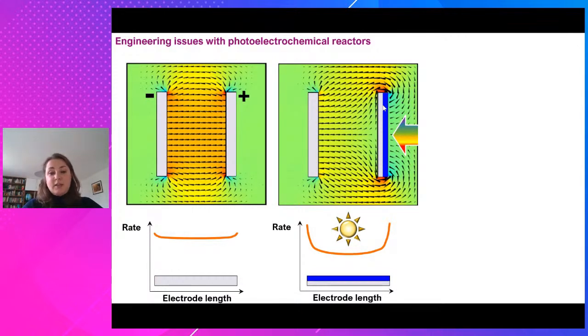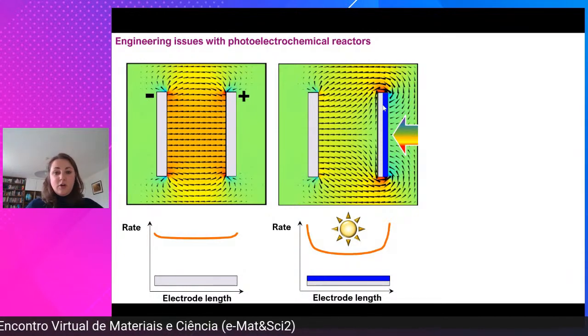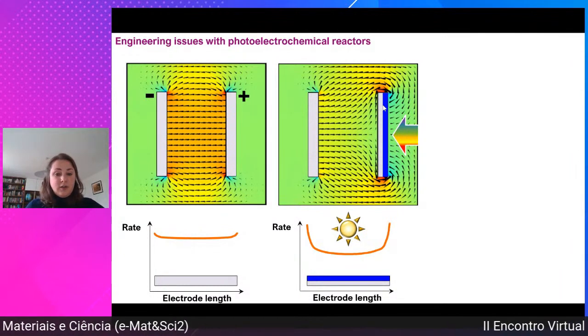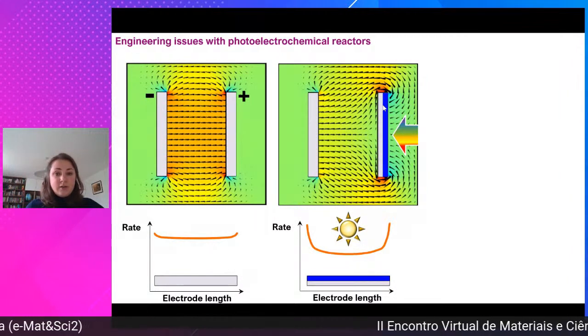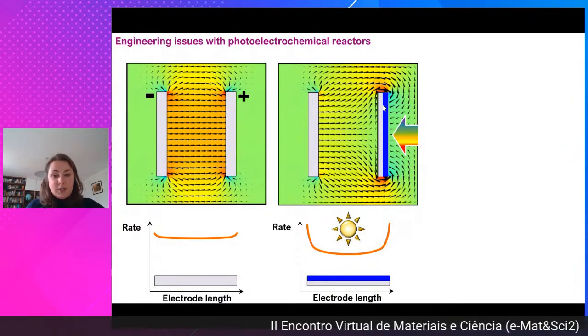And what happens is that the ions that flow between the electrodes to complete the circuit always choose the path of least resistance. It's the case for any charged species. And so the reaction rates become higher at the edges of the electrode and become smaller in the middle. So what that means is that if you scale up this electrode, for example, you want to increase your area, you make the electrode longer, it's not going to result in a proportionate increase in current because of this limitation.